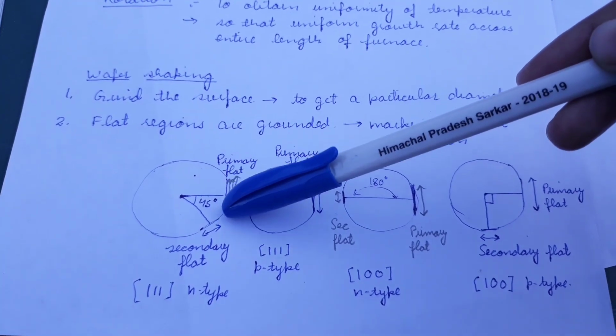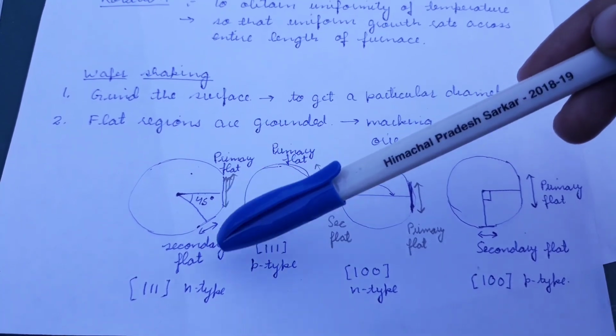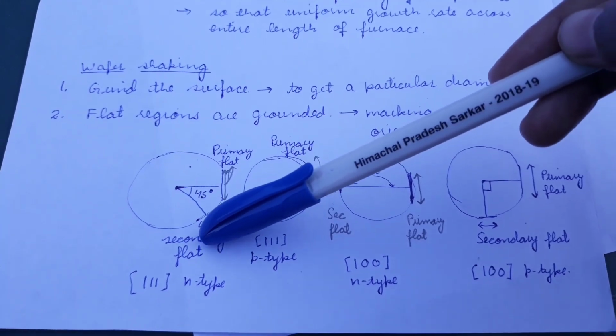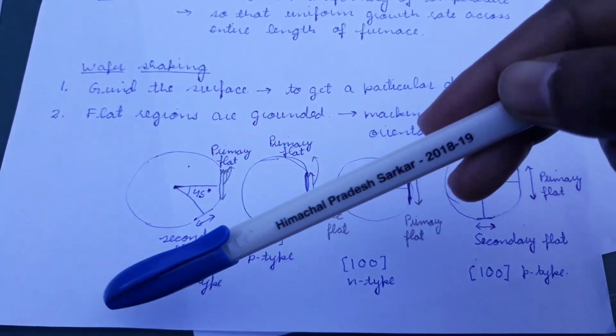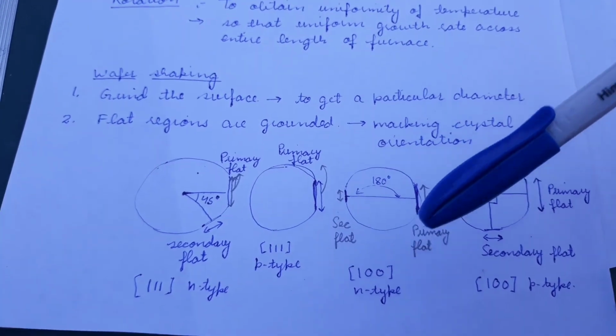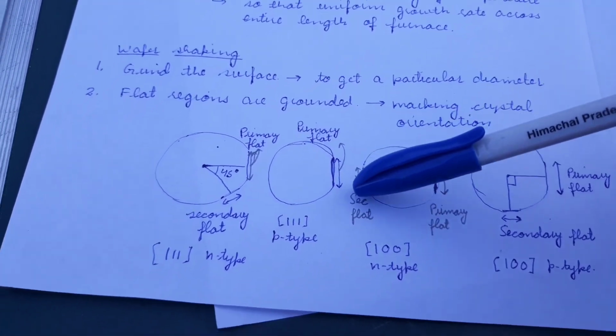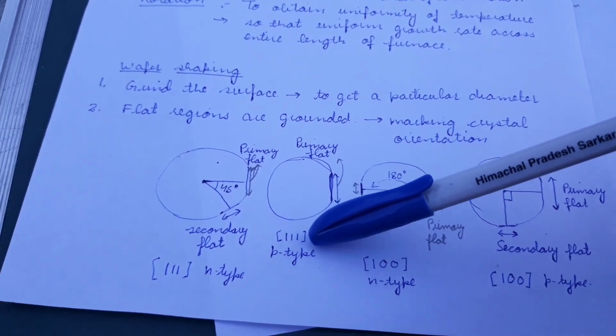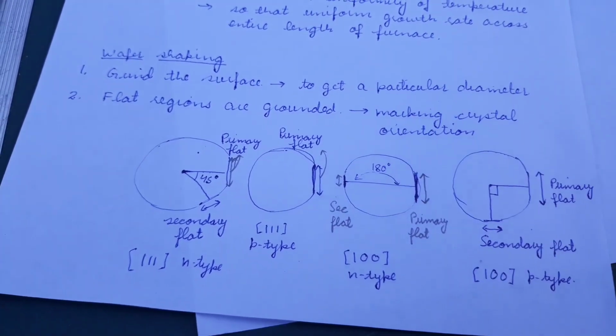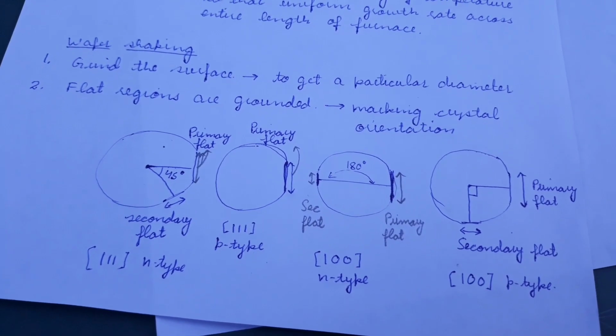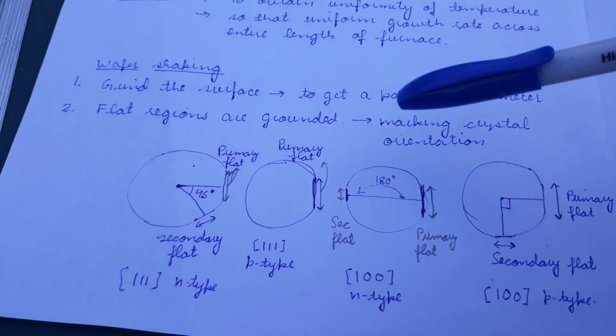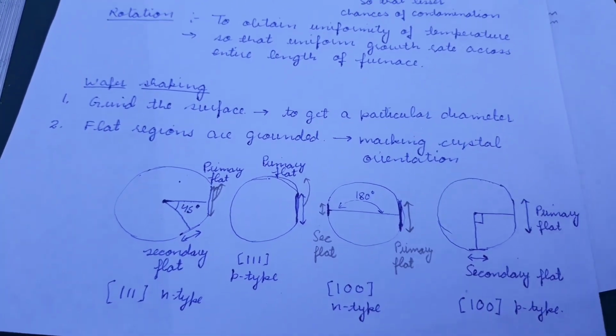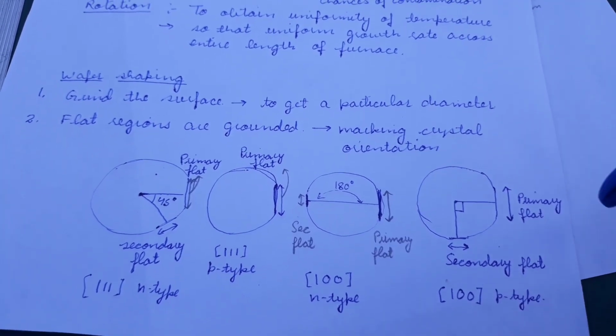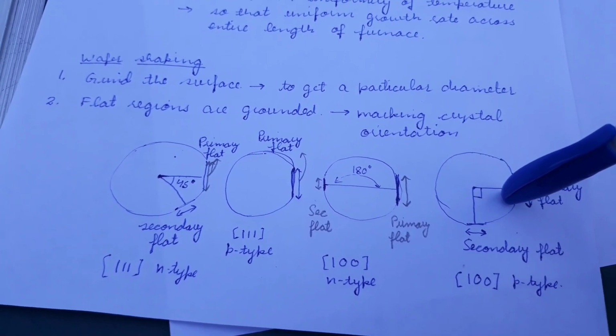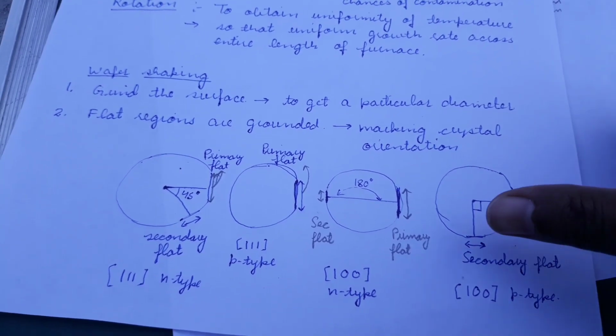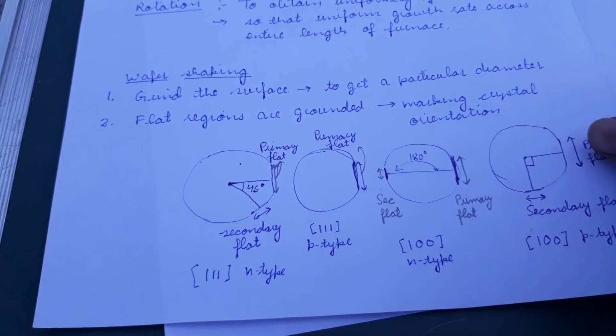If there is one larger flat, which is a primary flat, and a smaller flat ground on the surface at 45 degrees, it is a 111 N-type silicon wafer. If we just have one primary flat, which is a larger flat ground on the surface, it is a 111 P-type wafer. If you have two flats and they are 180 degrees away from each other, and one is primary and the other is secondary, secondary meaning a smaller flat, it is a 100 N-type wafer. While if the primary and secondary are at 90 degrees to each other, it is a 100 P-type wafer.